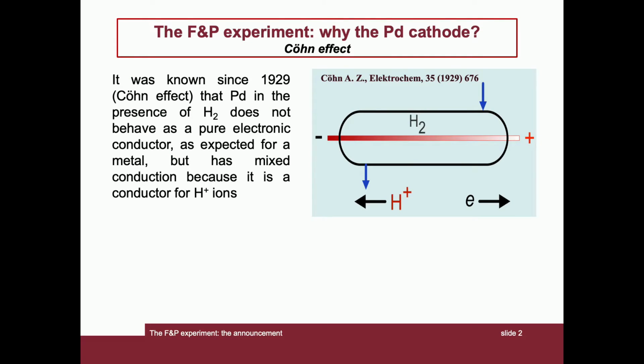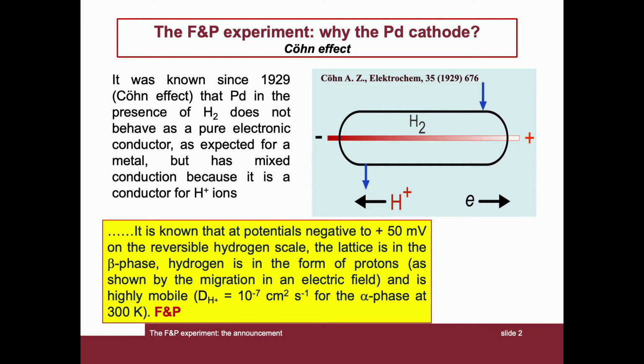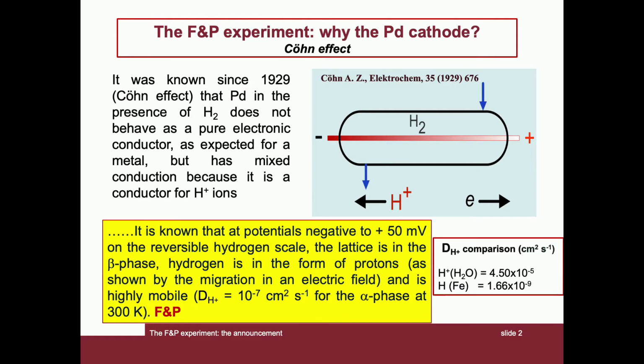The Fleischmann and Pons experiment. Why the palladium cathode? It was known since 1929 as the Cöhn effect that palladium, in the presence of hydrogen, does not behave as a pure electronic conductor, as expected for a metal, but presents mixed conduction because it's a conductor for hydrogen ions. The consideration reported in the article by Fleischmann and Pons is highlighted here, in which the proton state of hydrogen inside palladium and its mobility given by the high value of the diffusion coefficient are underlined.